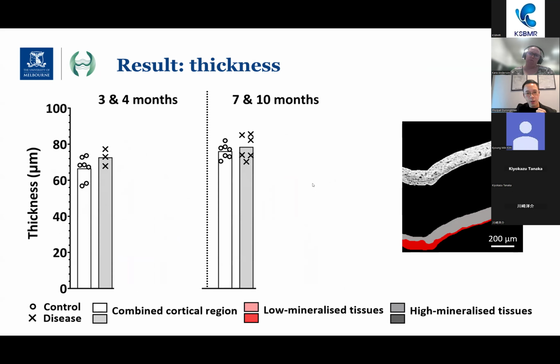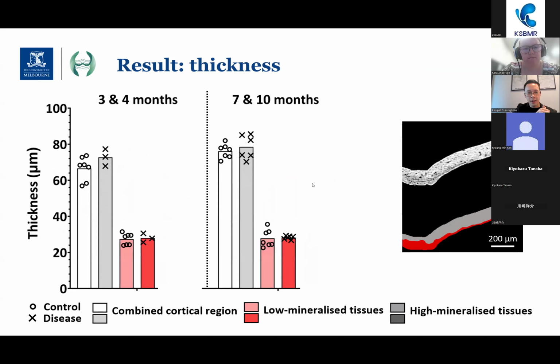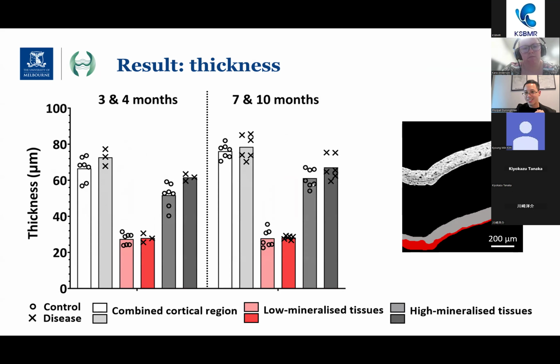And the next result that I wanted to highlight, we can observe the same thing for thickness. If we look at them as a combined region, as we would see in regular micro CT, then we can see that the lower mineralized region actually has a significantly reduced thickness compared to the higher one. And that kind of makes sense because thickness is kind of inversely proportional to porosity. So all those extra pores and all those rugged surfaces at the calcified cartilage interface actually play into the decreased thickness that we see in the lower mineralized tissue.